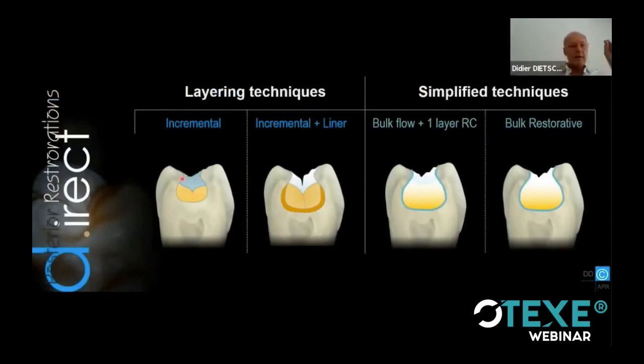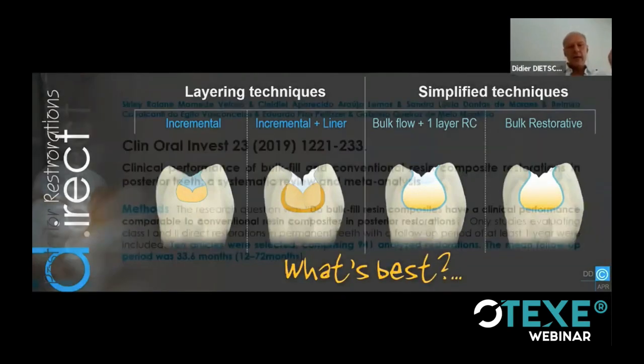Either conventional incremental, just layering, or incremental with a liner. The liner is usually a flowable material with slightly lower E modulus, so it's a little bit softer and works as a stress-breaking layer. Then there are new technologies, bulk flow, where you fill up basically the whole volume of the cavity and only keep a small layer for the surface, for which we use a restorative composite, or just a bulk filling material. You fill up everything in one step. What is the best? Which information do we have for this?